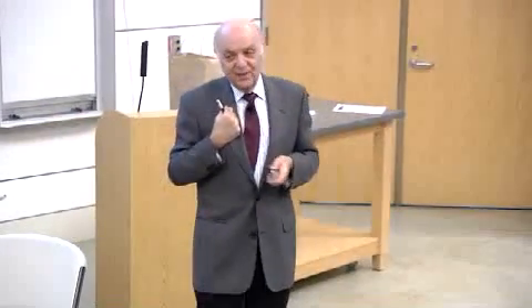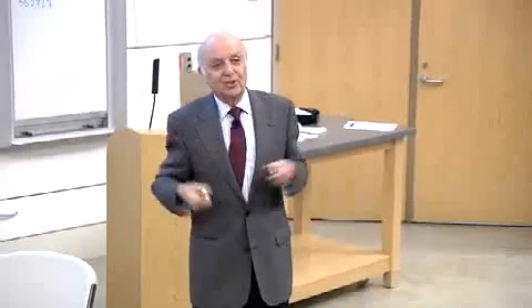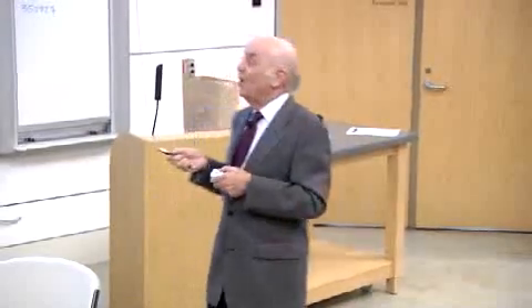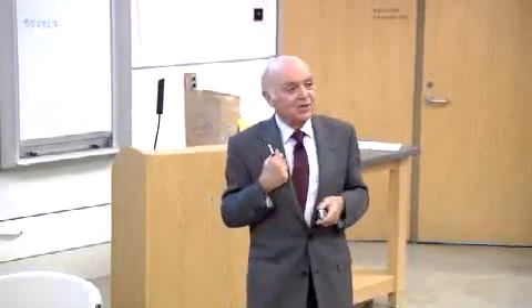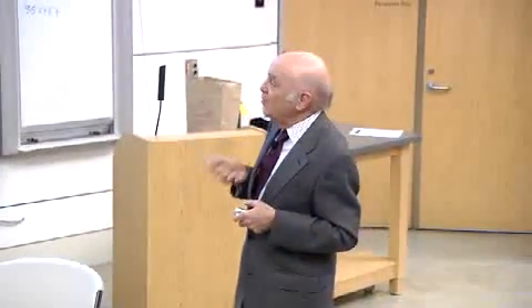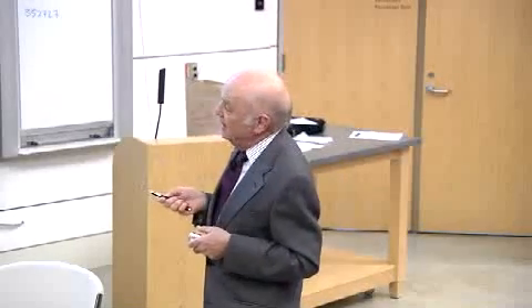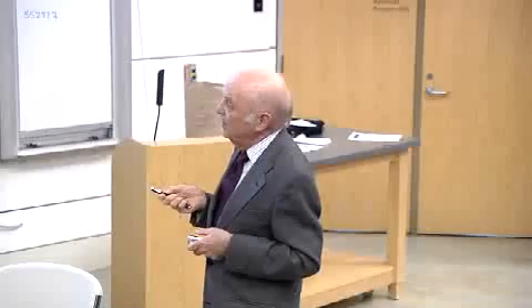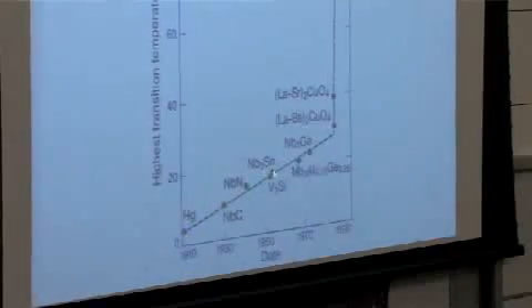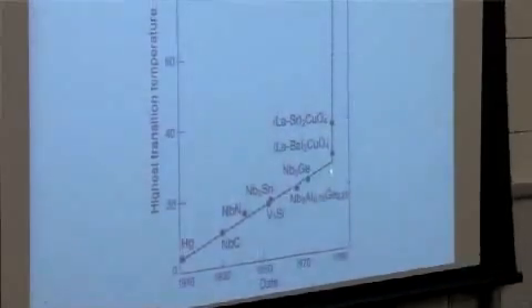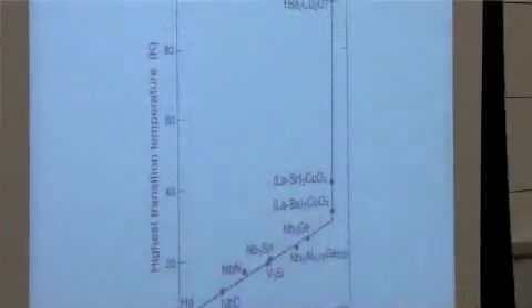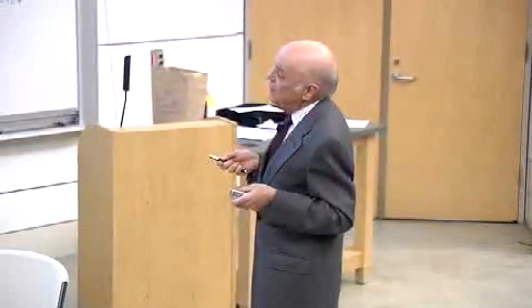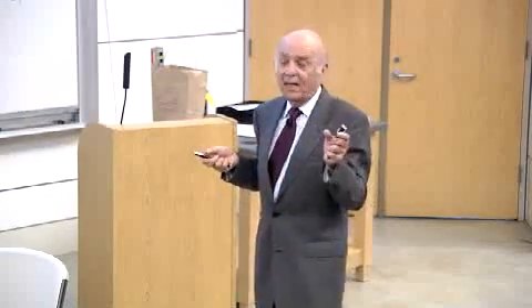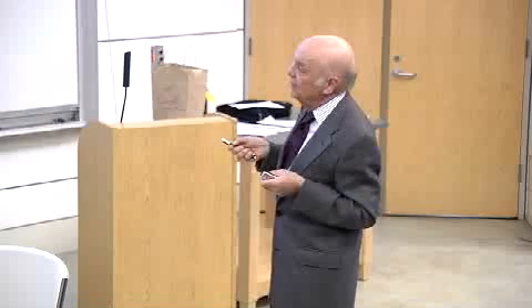And he thought that there was something wrong with his equipment, and Kamerlingh Onnes didn't believe it, but he accepted the Nobel Prize anyway. And the assistant went on to actually start the Philips laboratory, which is Norelco. And so the assistant did well. But Onnes, in his laboratory, investigated many, many materials for superconductivity. And as time went on, the highest temperature they could get at that time, first of all, mercury in 1911, was about 4.2 degrees on a scale we use, the Kelvin scale. I have to warn you that on the Kelvin scale, room temperature is 300 degrees. So this is a different scale than you're used to. But the point was, the degrees are the same size as the Celsius scale. But it was going up about 1 degree every 3 years.